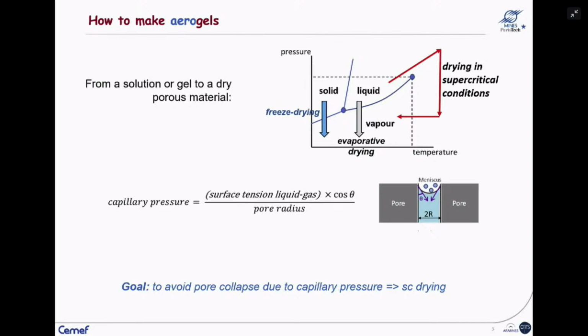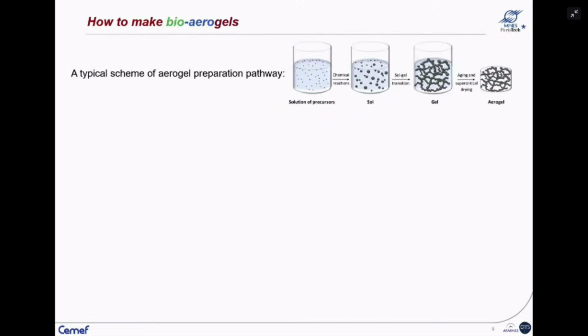So again, if you want to avoid the collapse of the pores due to capillary pressure, the way to do it is to use drying in supercritical conditions. It is possible to do freeze drying, but usually if it is done from water, the ice crystals that grow inside completely modify the morphology of the gel or solution. So the final material can be porous, but it will not reflect the morphology of the starting gel or solution, and usually it will not be nanostructured.